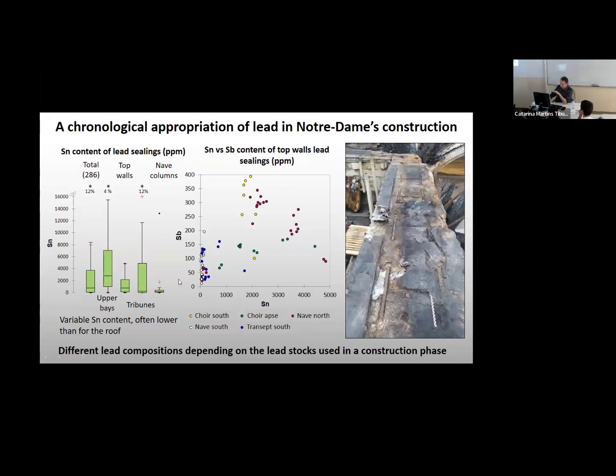And when you compare, not going into the details, with other elements such as antimony, which is also present in lead, you see that even for a single batch of lead, you can have really different compositions, meaning that you have different provenances, different sources that are easily being mixed in this spectrum.